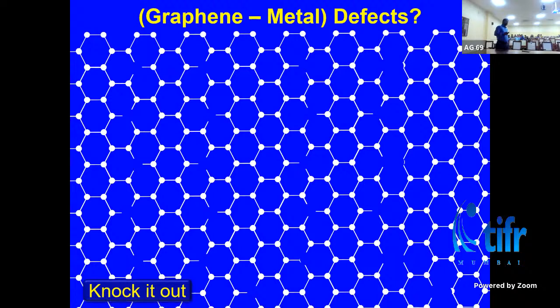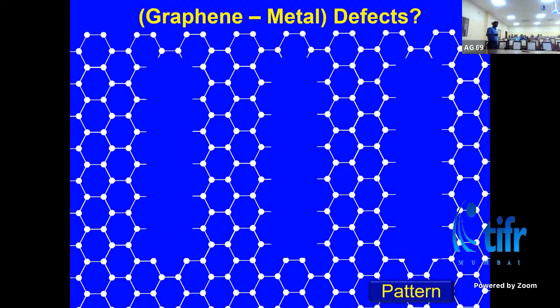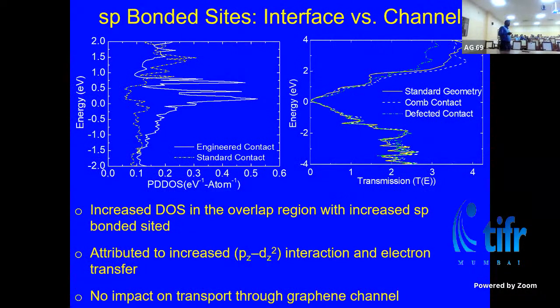Now in the case of graphene, if we knock out some carbon atoms, we create those sp bonded sites, I mean, the sites which are not fully bonded by, say, three other carbon atoms. Or we can also create these edge states by lithographically patterning or locally burning certain regions. So we further investigated that with computations, and what we found in the presence of metal, in this case palladium, is a huge density of states increment when we have engineered the contact. Which means when we have created these defects, or damaged the sp2 hybridization in those areas, and we bring in palladium in contact, we see a huge density of states around the Fermi level, and that basically signifies that now we'll have no depletion, we have decent charge transfer.